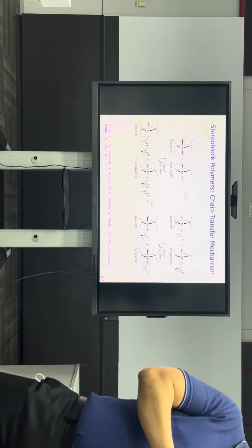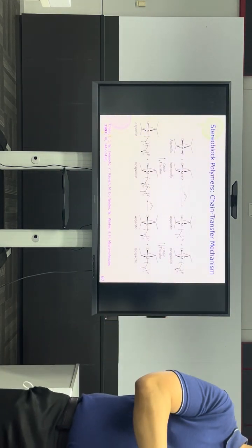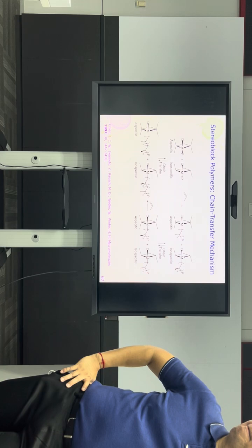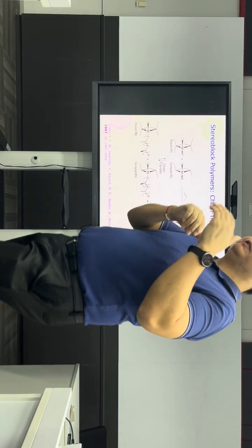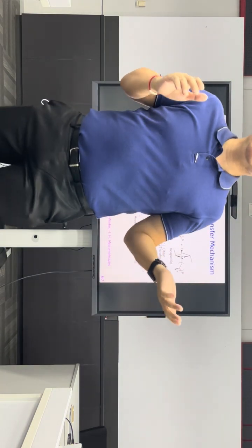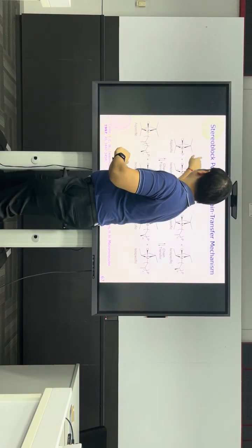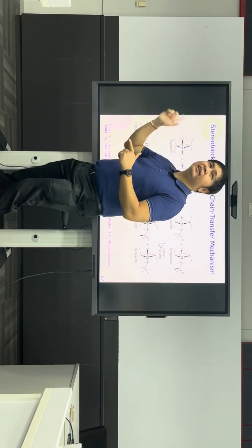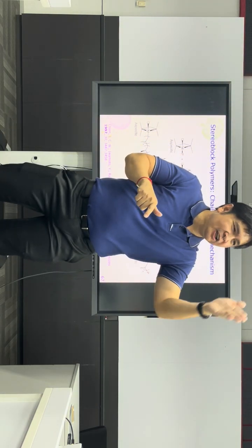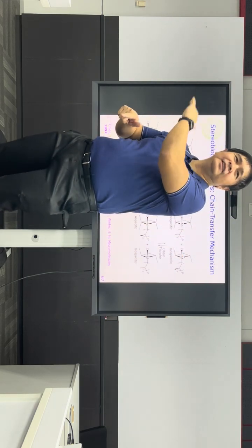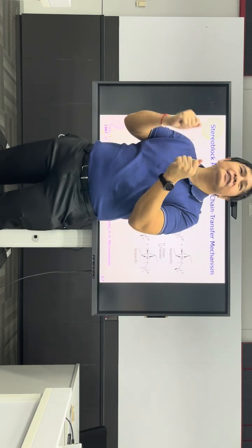For example, I think this is the last slide I show you, right? Okay. Another technique that people use is, imagine if you want to make a softer polymer, like a flexible polymer. Normally what people do is you get polyethylene, right? You have to copolymerize with hexene or octene so that you get a long chain of ethylene and then short chain hexene groups along the way. And when you have kind of a hanging group like that, the polymer will be flexible and soft.